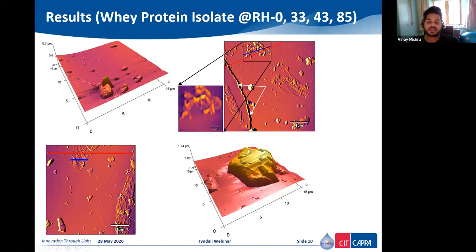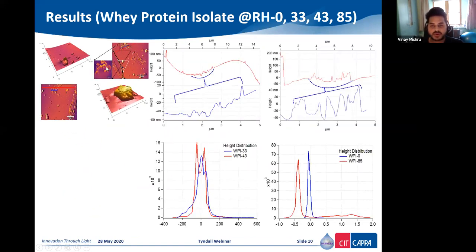Now they become more smooth as there is higher protein content in whey protein. It's around 90% in the powder which I used, and there are fragments everywhere. Now the orthographic projection of this region here is this one. It had a height of approximately 40 to 60 nanometers, and currently I'm not sure what they are.